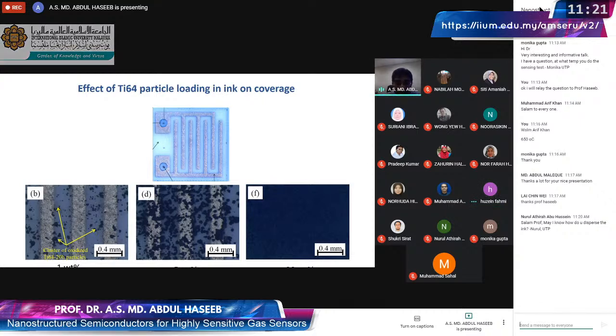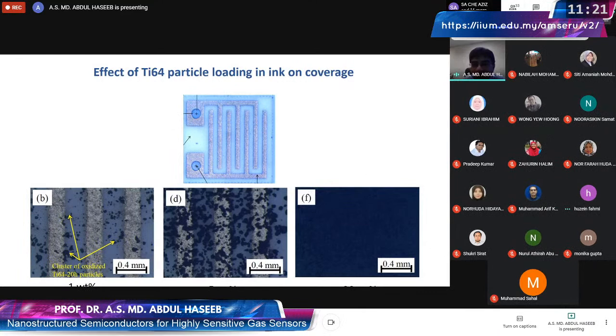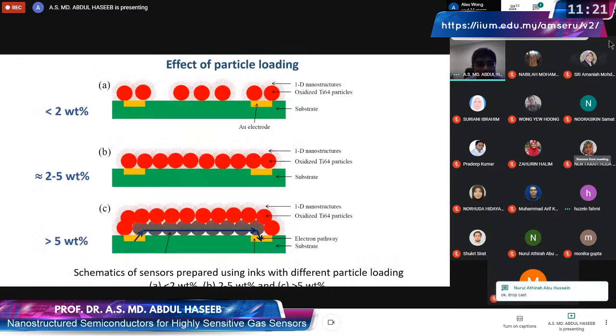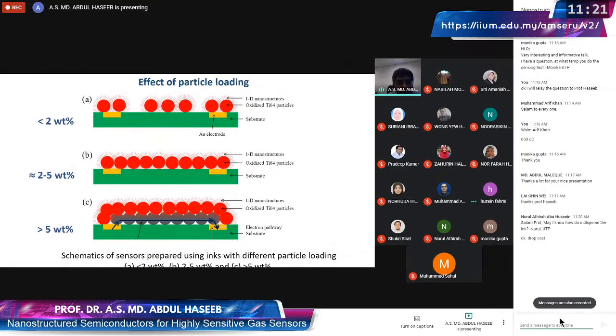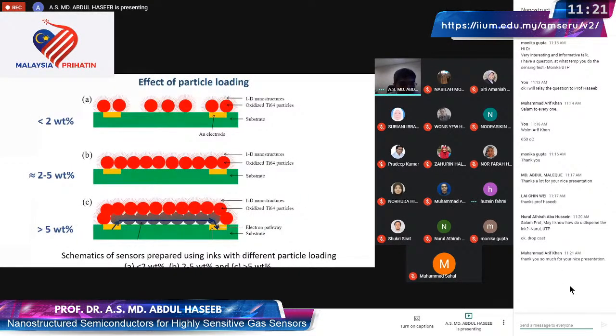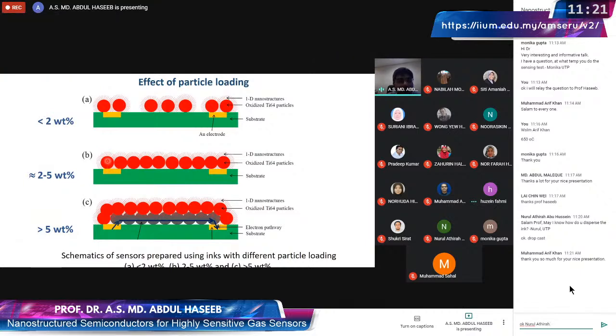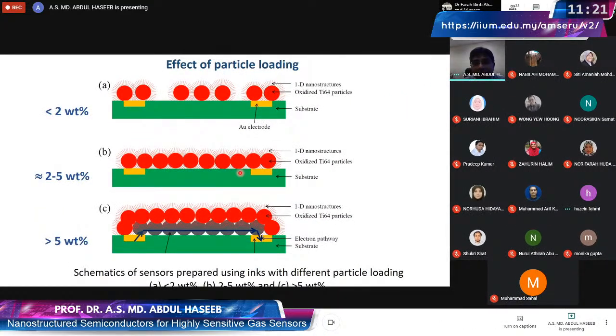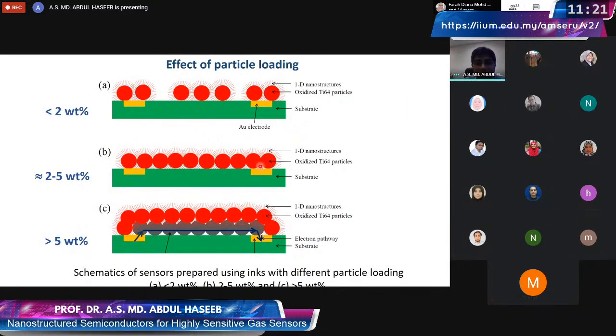The thickness is determined by the thickness of the particle. Let me show you this one. Basically, in the ideal case, we would have this. Let me have the marker. So we would have this, and the thickness that you see is the thickness of the particle, which is a few micrometers. And we want them to touch just on the surface at the outer nanowire contacts.